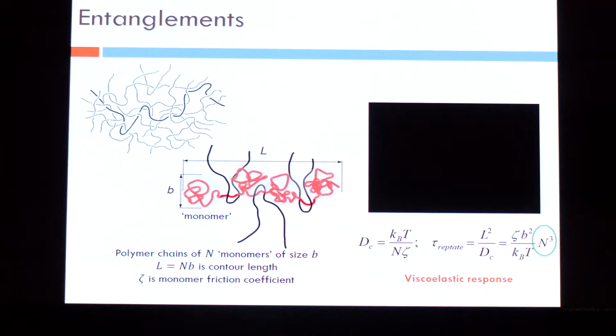And therefore, if you double the molecular weight, it takes much longer for the polymer chain to slowly relax from the stress that you have subjected the polymer chain to. It's a very slow relaxing polymer chain. Now what happens because of this slow relaxation? If I have stretched the polymer and I don't give it enough time to relax, this polymer is going to behave as if it is a solid, because it's not relaxing.